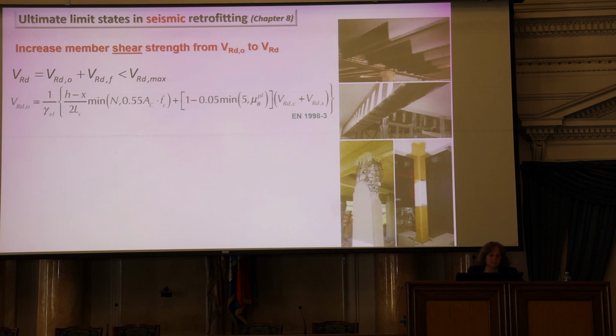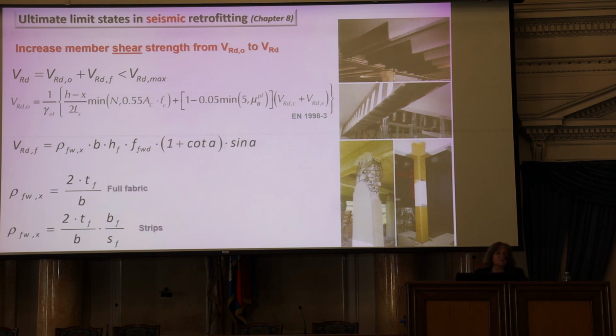To determine how much you need, you go with the classical approach for shear design. You have an initial shear resistance, that's the V_Rd,0 term, that's what you have. And V_Rd is what you want, how much you need. The difference between the two is what the FRP would need to take. And in order for you to determine how much the FRP would need to take, this is the expression for the FRP contribution. And in that expression, the unknown is the rho, the amount of FRP that you need to add, whether you go with a full fabric or whether you go with strips. And of course, you need to account for the anchorage conditions of your FRP jackets in order to see how much force you are going to put in them.